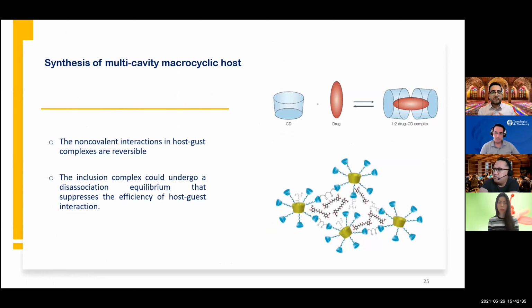again, when we are using host-guest chemistry, it's really good. However, as I mentioned, it's based on some non-covalent interactions. So maybe host-guest is a reversible equilibrium. So maybe we can see some reduction in the efficiency of host-guest interactions. And if we want to solve this problem, we can use the multi-cavity host, and it means that we can produce some multi-cavity that are already covalently interacted with each other. So we have a bunch of curcumin that's already separated and already incorporated inside of those baskets, and we can use those systems as a multi-cavity, as a new host for those things.